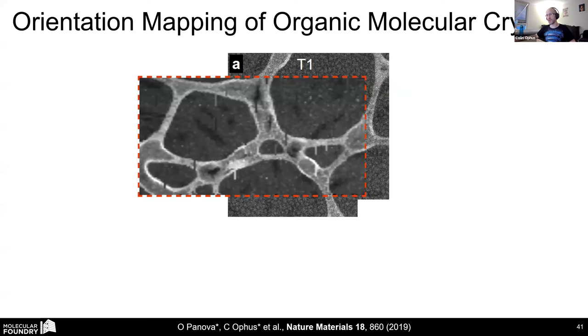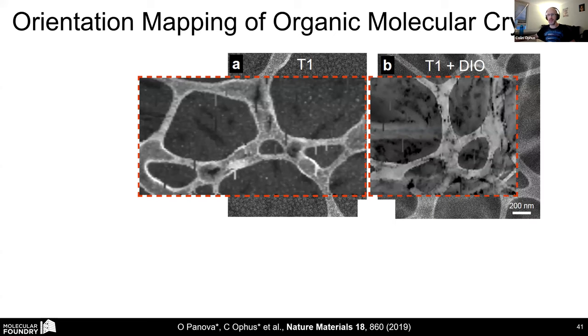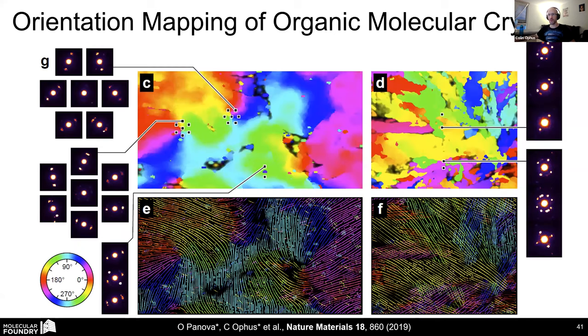This is just to really emphasize why we do these techniques. Here's the conventional HAADF imaging of the material without the additive and with the additive, and you cannot see anything. You can see the carbon grid, the lighter contrast regions there, but other than that, there is no morphological information about the sample. But if we replace that with the 4D-STEM measurement here, we get this rich picture of the local structure of this material after it's been spun onto the grids.